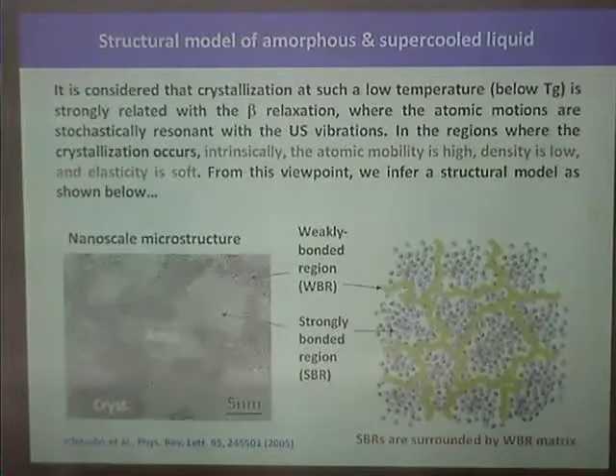But also for people who are experts, suppose you didn't use ultrasound to nucleate, but somehow you got nucleation out of an amorphous phase rather than a liquid. What's known about the morphology of nucleating crystalline droplets? Well, I think, typically you have an isolated event that grows, even in amorphous aluminum alloys, where you get crystalline nuclei about this size, 5 to 10 nanometers. They're clearly distinct from one another, and completely surrounded by an amorphous region. So it's an isolated nucleation event and then growth.